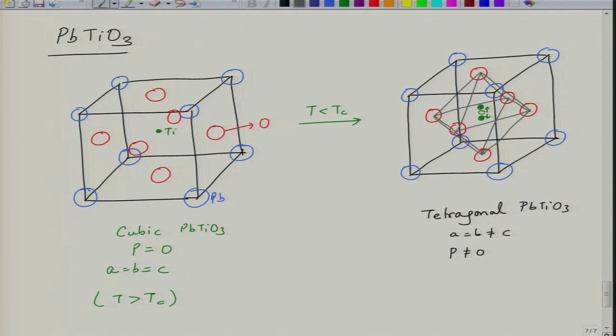And the oxygen octahedra will have a net charge of -4. Titanium has +4 charge. So let's say if you do a dipole moment calculation, when the center of negative charge and center of positive charge match with each other, when it is in cubic form, so these pluses and minuses match each other, as a result mu is equal to 0. So this is for this case.